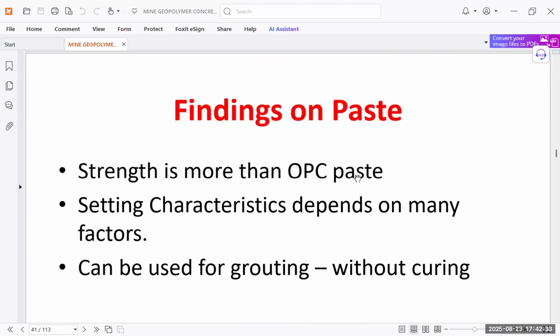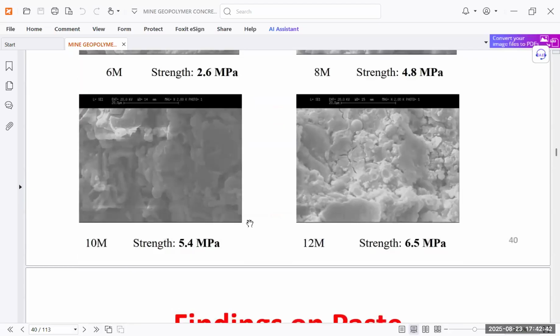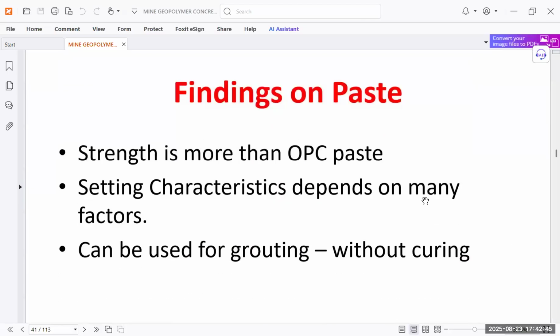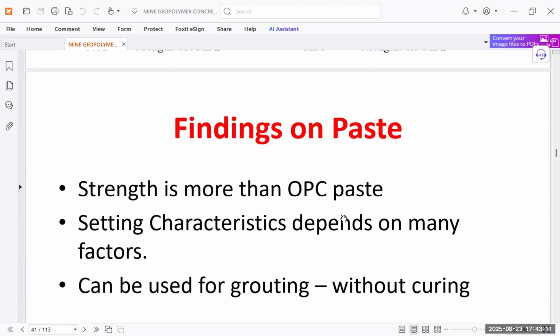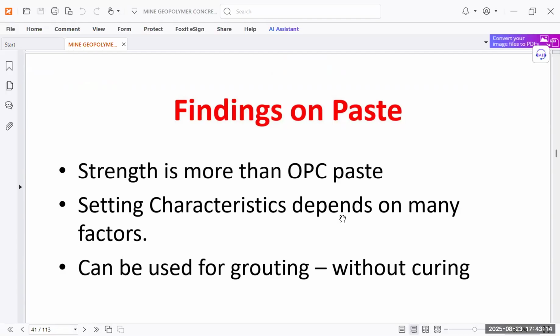Then the findings on paste: after this research, we find that strength is more than OPC paste. You can see that it is achieving strength by changing molarities. Setting characteristics depend on many factors, like initial and final setting time, and it can be used for grouting also without curing. That is also one important part, because curing water is required, but in this case water is not required. So grouting is done without curing, and we are saving water also. That is why the findings on paste are very much on the positive side, so that we can get the required strength.